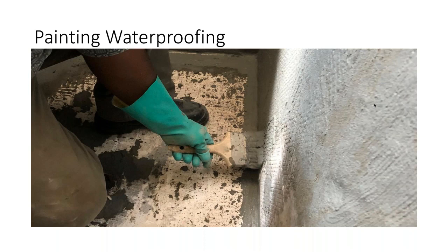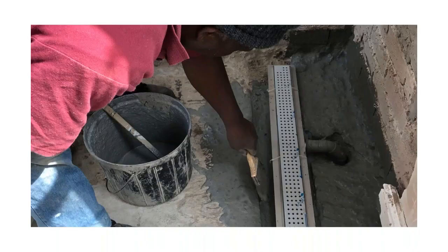When placing the trap into the floor, paint the latex layer all around the trap before putting in any topping. Even on an unplastered brick wall, paint the wall to waterproof it before plastering — this also gives a good grip for the floor topping. The pipe coming out from the trap is painted as well, and the trap itself is painted so that the cement topping gets adhesion onto the plastic PVC. Without this coating, cement won't grab onto smooth plastic.